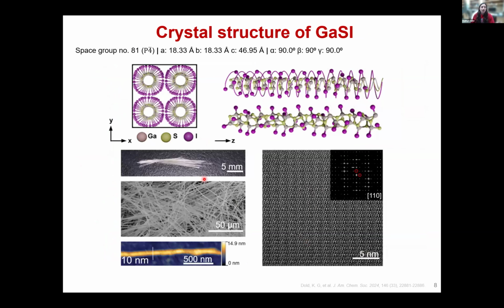Then I performed a detailed structural characterization of this material to look at its crystal structure and exfoliability. We can see that this material crystallizes in the non-centrosymmetric P4 bar space group, which we found through single crystal X-ray diffraction, and that it does retain its helical structure and looks pretty similar in the single chain to the gallium selenium iodide material.